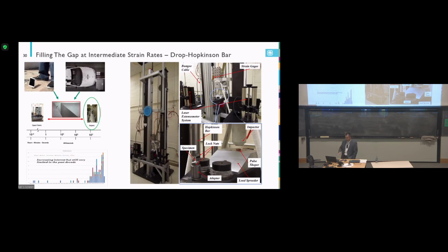So here is the drop table. You can see this is a drop table, and that's a vertical Hopkinson bar, and we have some kind of fixture beam on there, a wave diversion beam that Professor Lee helped me with many years ago. And you can see the sample is about here. That's a tensile sample here. So this is the impactor. It drops a big weight, then pushes everything down, then pulls the sample. Then we use a Hopkinson bar to measure the force, displacement, everything. We have a stress strain curve.